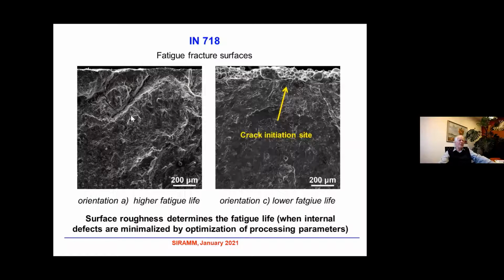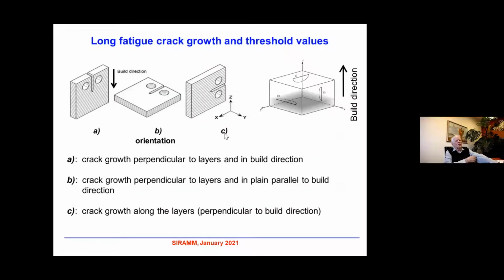And on the left-hand side, you can see this relatively flat surface, higher fatigue life. The crack started somewhere here and propagated in this direction. On the right-hand side, orientation C with not so nice surface, lower fatigue life, and the crack initiation site was nearly in this region. So surface roughness determines the fatigue life naturally when internal defects are minimized by optimization of processing parameters. Once more, I repeat that to remove internal defects completely is practically impossible. So the next thing is the problem of propagation of long fatigue cracks.